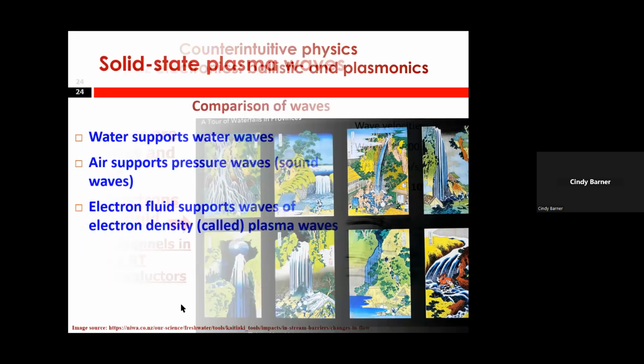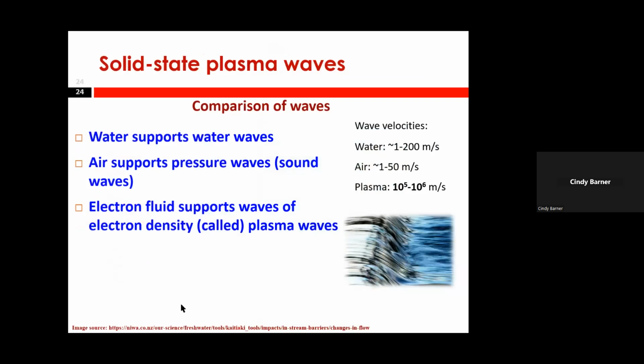So, in a nutshell, water supports water waves, air supports pressure waves, sound waves, but electron fluid supports waves of electron density. These waves are called plasma waves. The velocities are, for water waves, from 1 to 200 meters per second, for sound waves from 1 to 50 meters per second, and for plasma waves, which are waves of electron density, from 10 to the 5th to 10 to the 6th, more likely something around 10 to the 6th. So only about 300 times smaller than the speed of light. It's very fast. Therefore, if we use plasmonic waves to build electronic devices, it's easier to reach terahertz electronics, easier to make terahertz devices using plasmonic regimes of operation.